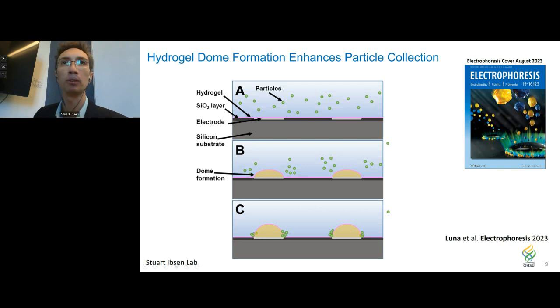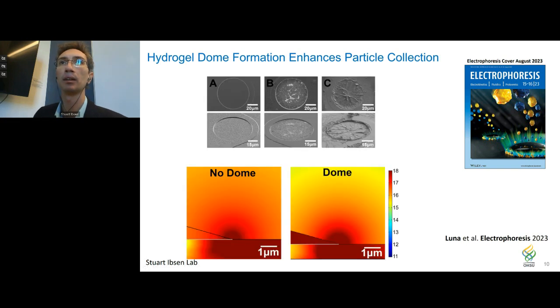So we did some computer simulations to understand how this works a little better. First, we looked at the actual domes themselves. These are scanning electron microscopy images of the electrodes, SEM images, where we were collecting particles from human plasma. Then we freeze-dried the chip, lyophilizing it to get rid of the water, and took a look at the actual electrodes under SEM. We can see all these crinkles on the surface, which we believe are left over from the dome forming. When we freeze-dried it, the dome collapsed, but it left behind these creases showing that there had been earlier inflation of the hydrogel around that area.